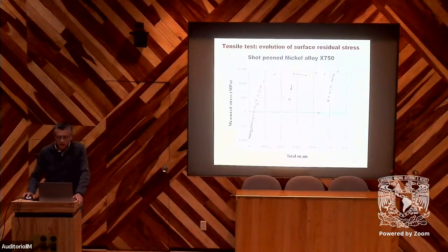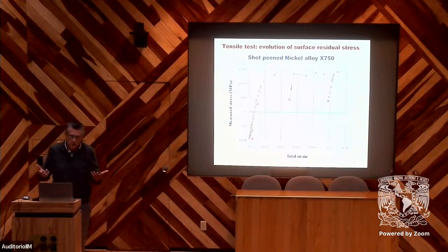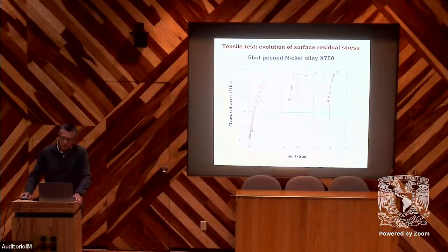So if we take this material after grinding, of course we have very high compression near the surface at the beginning. The question is what happens when we apply some stresses or some load. We can observe here the total stress, that means what we measure when we apply stress, the real stress. And now if we unload at each step, we can see the evolution of the initial residual stresses. And we observe that the residual stresses change very, very quickly, and this will be stabilized at a positive value, 500 megapascals. And we started from minus 900 megapascals.